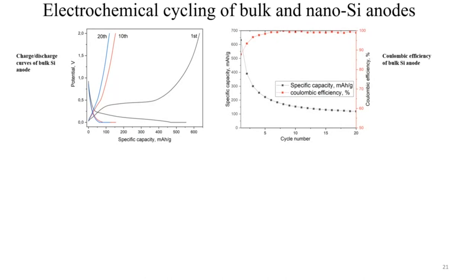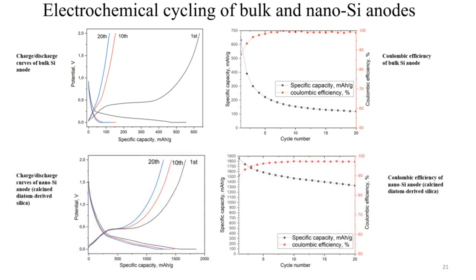So the electrochemical performance of recovered silicon-based anodes was also compared with that of bulk silicon. And as can be seen here, for bulk silicon, we see a very rapid decline in capacity from the 1st to the 10th and also to the 20th. And this is also evident in the coulombic efficiency chart here, where we see this decline in capacity. But in the case of the nano silicon powder, we see a rather slow decline in the specific capacity.